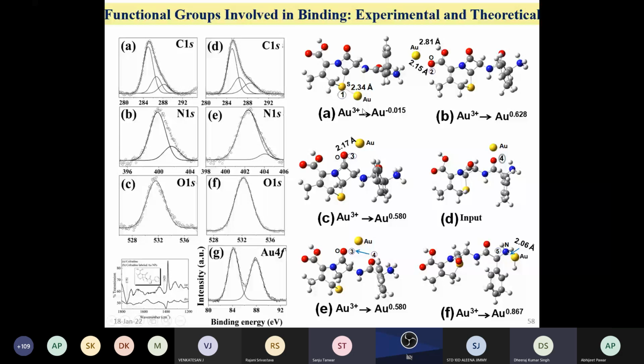nanoparticle. This sulfur plays an important role, because in chloroauric acid gold has a +3 charge, but when we mix the gold at the sulfur place, gold gets a negative charge in the gold nanoparticle, and the reducing property of sulfur is much larger than oxygen. So we can find out that our antibiotic molecule successfully reduces HAuCl4 into nano form, as well as binds with sulfur and oxygen to the gold nanoparticle, which stabilizes your particle for several months.